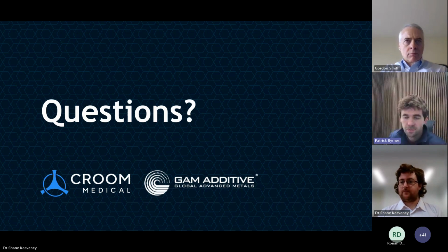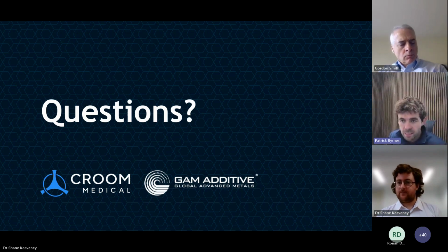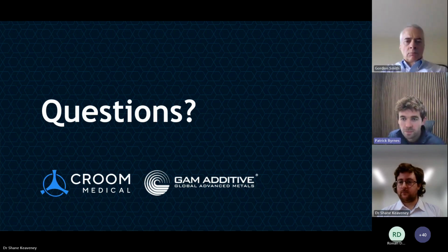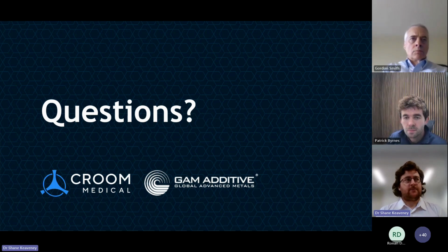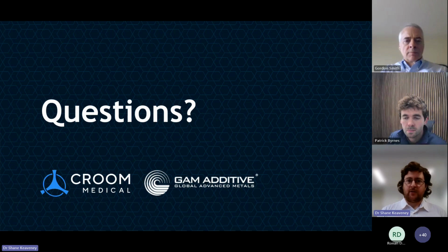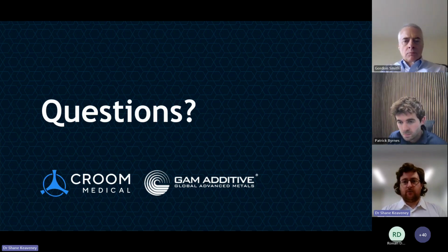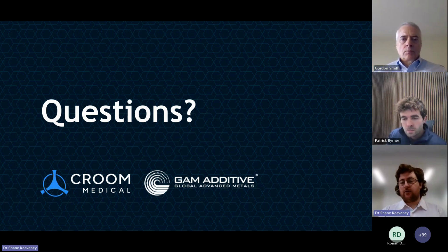And building on that, what significant challenges did you face in bonding the tantalum and the titanium material within the laser powder bed fusion process? Significant challenges. I think again, it's around the DOE of the print parameters. So trying to understand what kind of energy we need to input there to have a strong bond, and also not to have some deformation or some issues or burning of the aluminium or vanadium out of the titanium. So again, just really working with the print parameters. With this machine, obviously we have full access to change whatever parameters we need, and we've a good understanding from our experience here around how to do those DOEs and how to work with the print parameters. So that's been some of the main challenges.